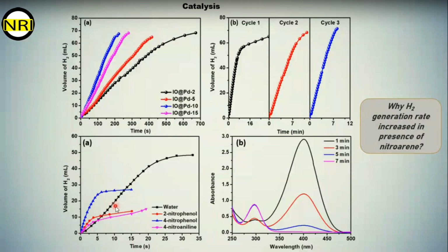Here you can see this black graph is for the hydrogen generation reaction in presence of water. But when I am using some nitroarene compounds, the rate of the reaction is increasing. This is because the nitroarene compounds allow the ammonia borane to adsorb on the catalyst surface. If more ammonia borane adsorbs on the surface, then more hydrogen will be produced at a time, and the rate of the reaction will increase. The difference between 2-nitrophenol, 4-nitrophenol, and 4-nitroaniline rates is maybe due to the adsorption properties of the catalyst surface and the nitroarene compounds. And one more thing we can see is that the complete production is not happening when we are using nitroarene compounds.